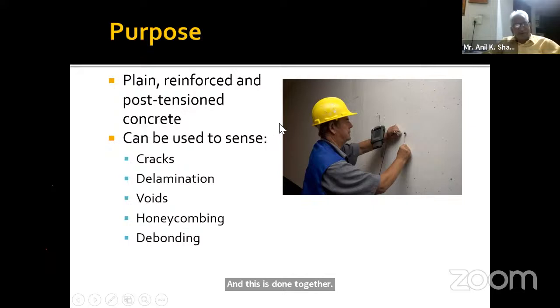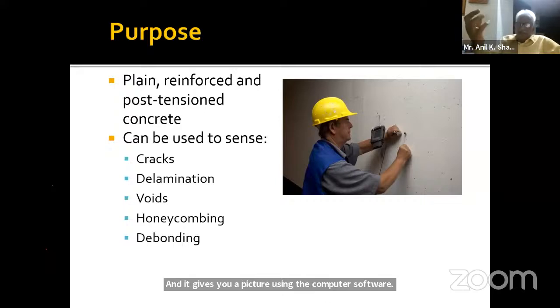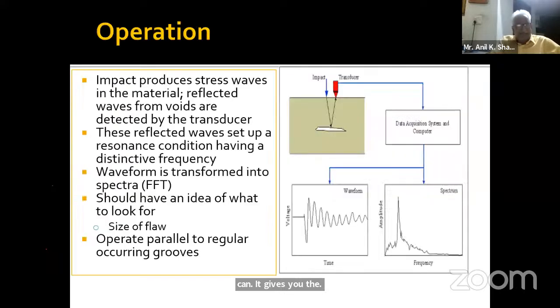It is used for plain reinforced and post-tensioned concrete. It can be used for sensing cracks in the structure, delamination, voids, honeycombing, and debonding, and it gives you a picture using computer software. It gives you the reflected image of the defect in the structure. So say for example, this is a void. The impact is given here, and the transducer receives it back. So it gives you the location of the defect, and also the thickness of the member.